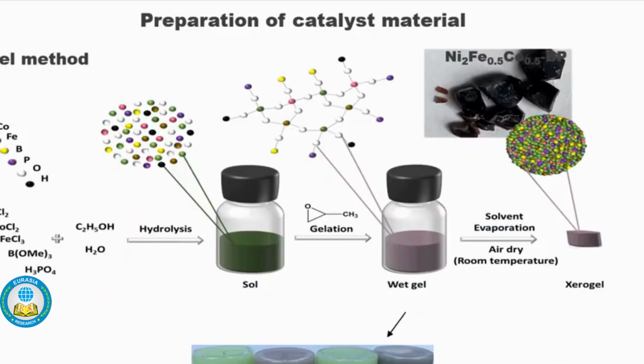In this work, we used a sol-gel method to prepare the multi-elemental electrocatalyst, which is one of the mainstream methods to produce multi-elemental materials and also permits charge distribution between different elements. The nickel, iron, cobalt, boron phosphate material was prepared by using a modified aqueous sol-gel method using metal chloride precursors, trimethyl borate as a precursor for boron, and phosphoric acid as a precursor for phosphate, as well as an acid catalyst for hydrolysis and gelation processes.